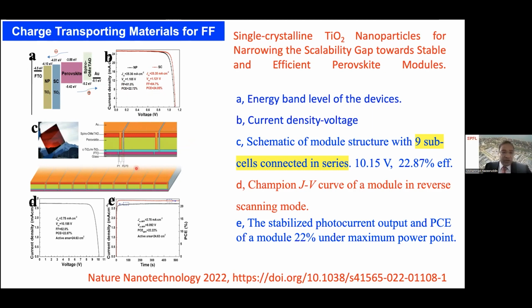And using this new ETL layer, we also built these 9 cell mini modules. The 9 cell mini module gives you 10 volts VOC for the system, and the power conversion efficiency is reaching very close to 23%. The beauty here is that the smaller cell, at 24% efficiency, has a size of 0.15 square centimeters. Here we have a size of close to 25 square centimeters, but still the efficiency is 23%. So in these perovskite solar cells, the take-home message is we have reduced the efficiency gap between the small cell and the larger cell.